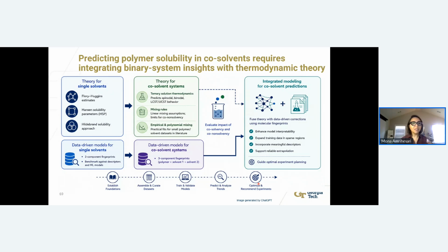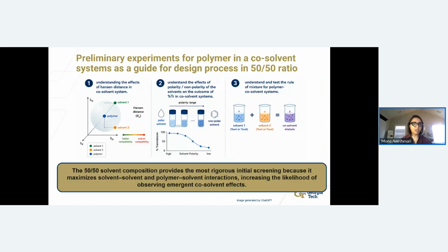So we needed to go back and run some validation experiments. We had some single-solvent data from the theory, from Flory-Huggins, Hansen solubility, and Hildebrand. We have some theories for the co-solvent system. We also have data-driven approaches for the binary polymer and solvent system. And we have something that we also learned from the literature on the co-solvent system. Can we combine everything together for a physically informed machine learning model? So we are not only collecting the data, but we are bringing a theory for a more complex system to learn from it. So the goal was designing a physically informed machine learning model that can facilitate the prediction of the co-solvent system.